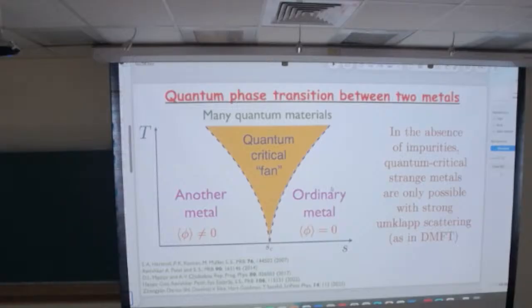When you look at the low energy theory of any critical point, there's a conserved momentum. And in fact, it was that conserved momentum that was responsible for the strong violations in the Wiedemann-Franz law that were measured here. So there's a similar thing here, not quite exactly the same. But the conservation of momentum in the low energy theory implies that even though you may break down quasiparticles in this regime, the strange metal transport simply does not appear.